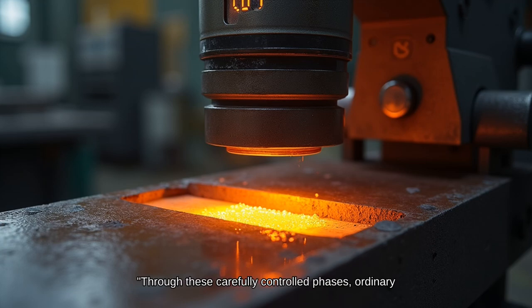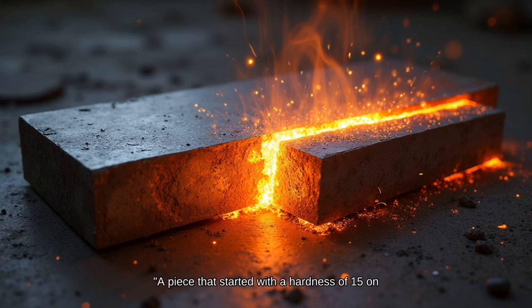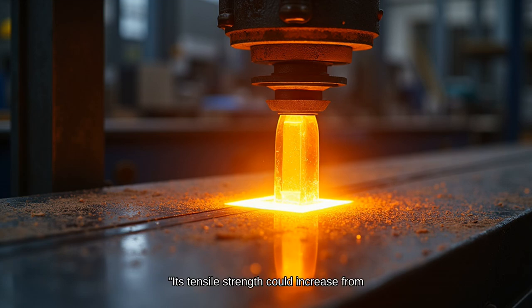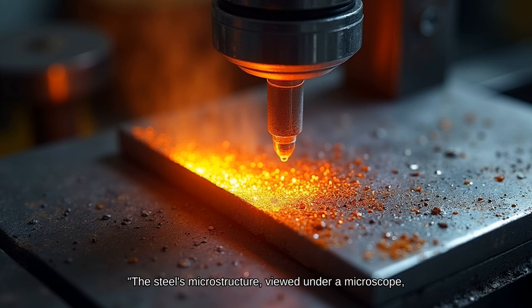Through these carefully controlled phases, ordinary steel is transformed. A piece that started with a hardness of 15 on the Rockwell C scale might now measure 60, harder than a file. Its tensile strength could increase from 70,000 psi to over 200,000 psi. The steel's microstructure, viewed under a microscope, reveals a complex landscape of martensite needles, retained austenite, and carefully distributed carbides.